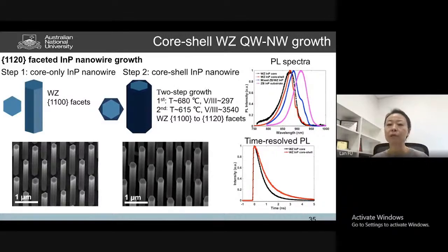A limitation of that is we can only grow very short quantum wells. So they're fine, short nanowires. Short nanowires are fine for some applications. But for other applications where we actually want longer nanowires with larger active volume, as well as a controlled design of the nanowire structure or optical cavity, we want the flexibility to grow nanowires with controlled length and diameter. So how can we do that?